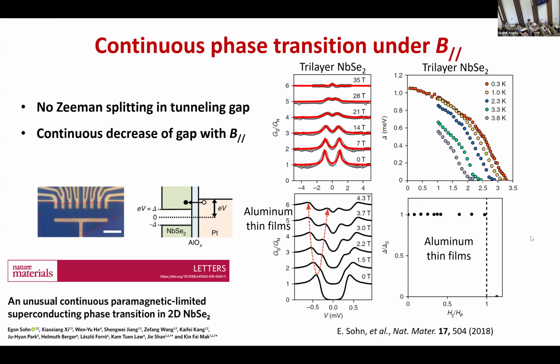In the aluminum thin film, you have a first order transition, and when you have enough Zeeman splitting, you kill superconductivity, and suddenly the gap closes. But this is not the case in niobium diselenide. So this feature is also claimed to be related to Ising superconductivity. Basically, you continuously rotate the spins, so that suppresses superconductivity. So yeah, this is another feature people claim.